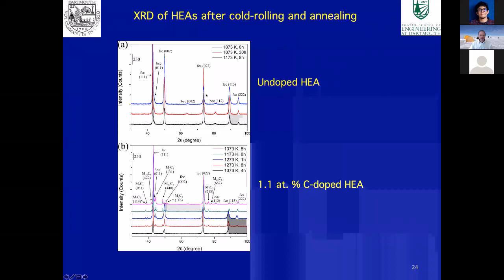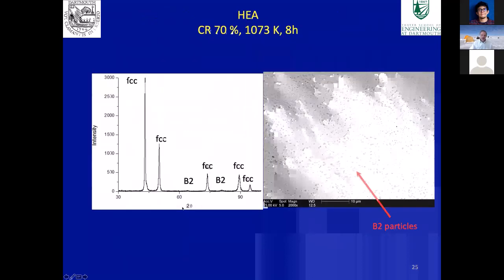So looking at what we have after the typical anneal, for the undoped alloy, we had both face-centered cubic and second phase particles. They're labeled here as B2, but in fact they're ordered body-centered cubic. And for the carbon-doped alloy, which was annealed at higher temperatures, we've actually got some carbides forming in the material.